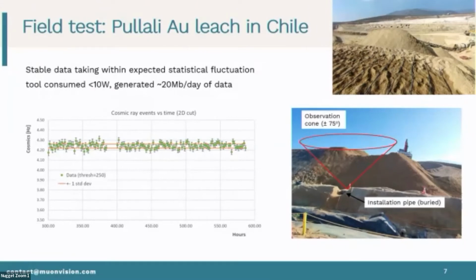The point I want to show you is that the measurement is statistical. Cosmic ray flux is low enough that you start seeing small variations, but it's stable. This is a physical fluctuation. The mission is that we want to distinguish between dry and wet. Already by walking on it, you hear different sounds, meaning different densities. Also keep in mind that cosmic ray muons come from all angles, not exclusively from the vertical. In principle, even from 80 degrees from the vertical, but things get complicated. So we try to limit ourselves to analyzing only the first 75 degrees around the vertical. This already gives a great coverage. At 10 meters, the base of this cone is the diameter.